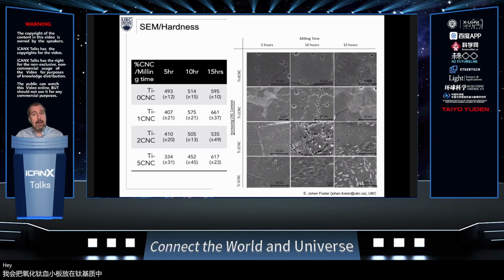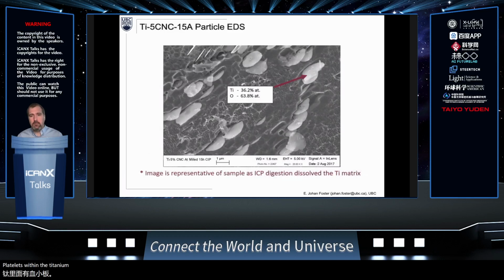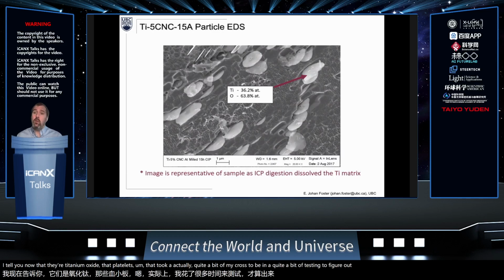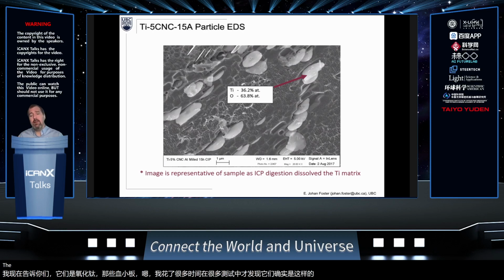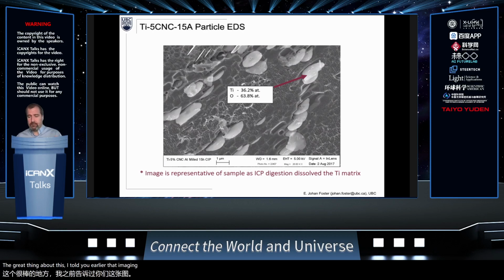Good. So the hardness increases as a function of the growth of those titanium oxide platelets within the titanium. I tell you now that they're titanium oxide platelets. That took quite a bit of microscopy and testing to figure out that they were. The great thing about this, I told you earlier that imaging our composites was very difficult with cellulose nanocrystals within polymers. Imaging titanium oxide within titanium is fantastic, just because of the contrast between these.